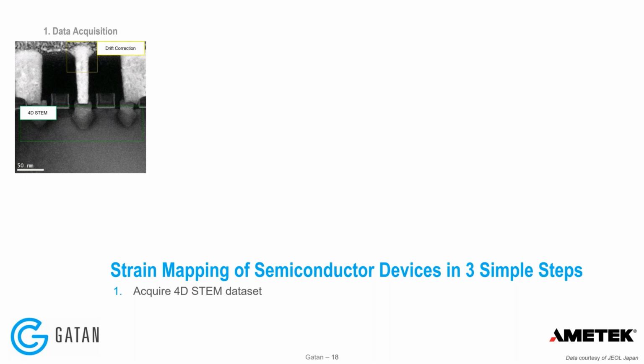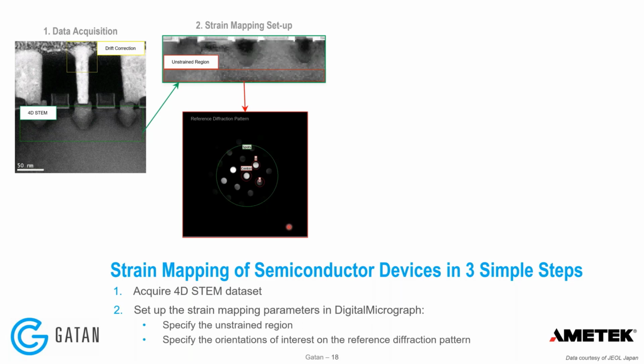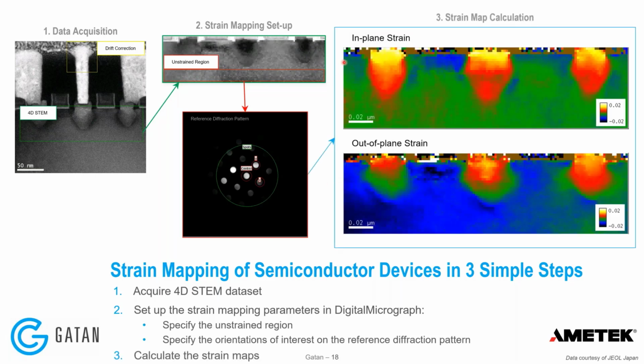So the way nanobeam diffraction and 4D STEM strain mapping works is you collect your data, of course. Once you have your 4D STEM data set, in the software, you specify a region of the sample that does not have any strain. That is shown here on this diffraction image. So I have specified this region in silicon closer to the substrate as an unstrained area. The software is going to calculate a reference diffraction pattern using the diffraction images in these pixels. Then you specify the crystalline direction for which you want to calculate the strain, and then the software goes pixel by pixel and compares the diffraction pattern in each pixel to this reference diffraction image and measures how much the distance between the reflections has changed.